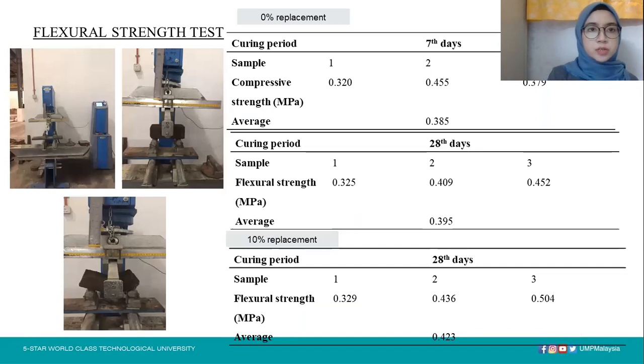This is for the flexural strength test. Same as before, for the flexural strength test, I obtained for the control zero replacement, 3 samples for 7 day and then 3 samples for 28 day, and the average will be taken. For 10% replacement, the average at 28 days is 0.423 megapascal.